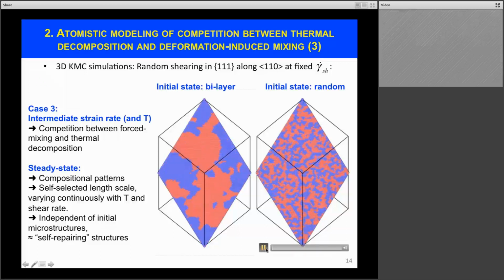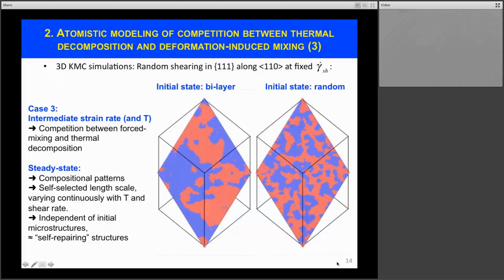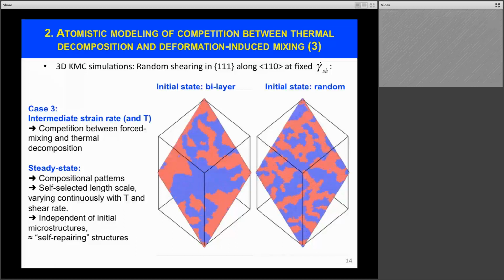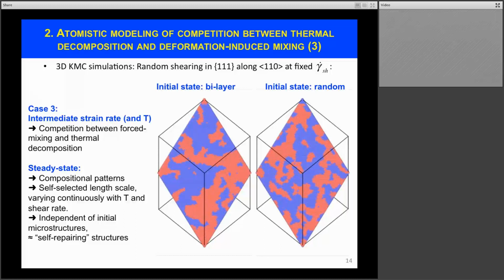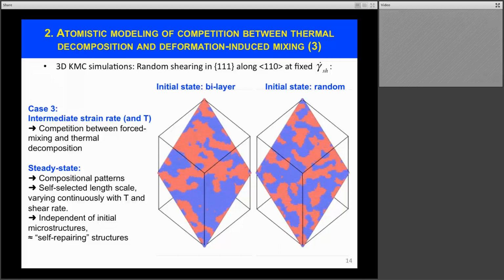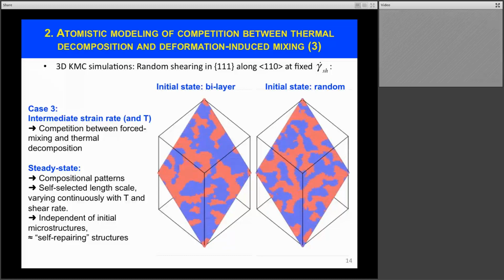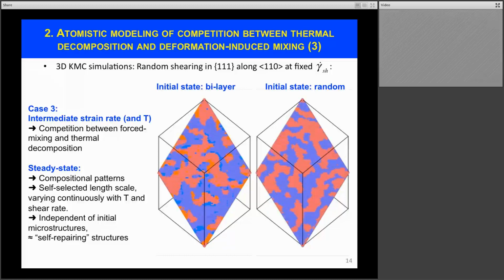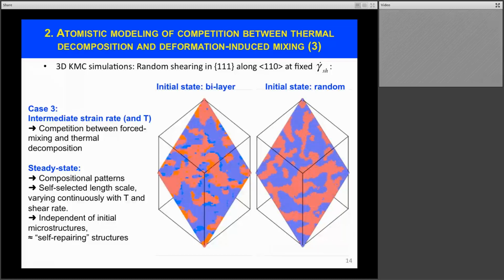And if I start from the random solution, on the right-hand side, you see that the system starts by forming regions that are copper rich and silver rich, or red and blue. But the remarkable point is that this phase separation never reaches the macroscopic scale. And so here, after a while, we would see that these two systems reach the same, or statistically equivalent, steady state. These steady states are like a two-phase system, but they have a finite length scale,